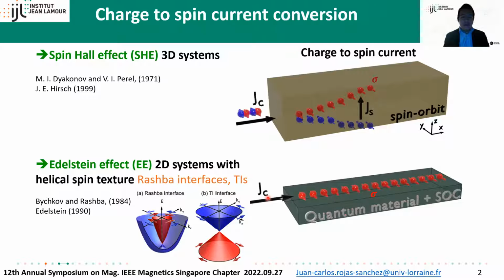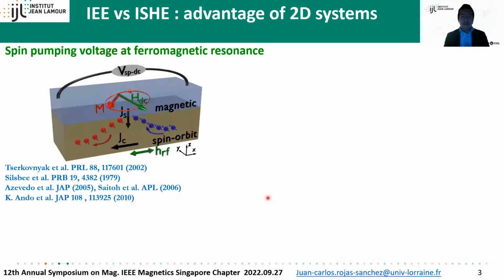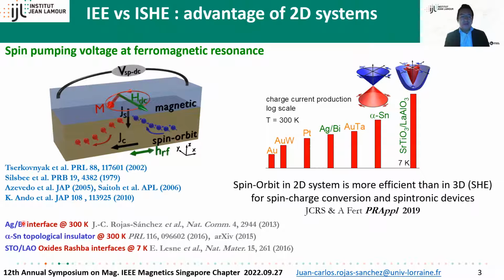Indeed, in the last 10, 11 years, I have studied this reciprocal effect a lot using spin pumping ferromagnetic resonance. I will skip the details, but just to mention that I studied different materials like platinum, gold, tungsten, gold tungsten, and also a Rashba interface such as silver bismuth, or magnetic oxide, or topological insulator alpha-tin at room temperature. What we can observe is that, as predicted and expected, we observe a larger efficiency. We have a gain using, for example, the alpha-tin topological insulator at room temperature, or this Rashba oxide at 7 Kelvin at lower temperature. This is a log scale. So the gain here between alpha-tin and platinum is a factor 10, for instance.